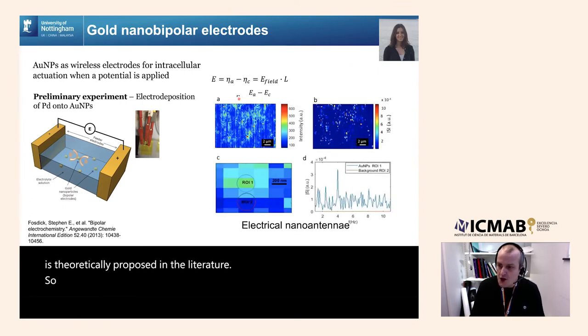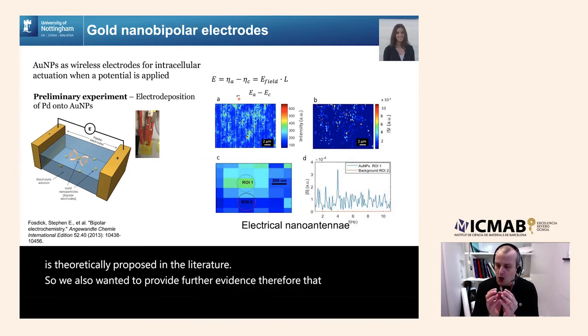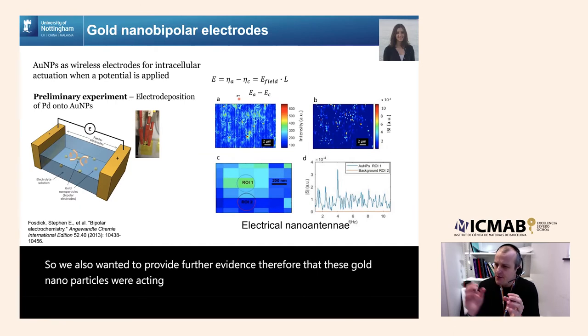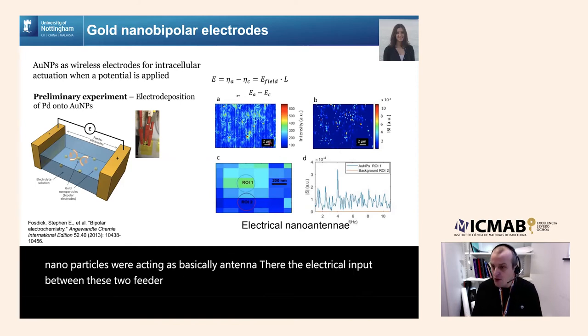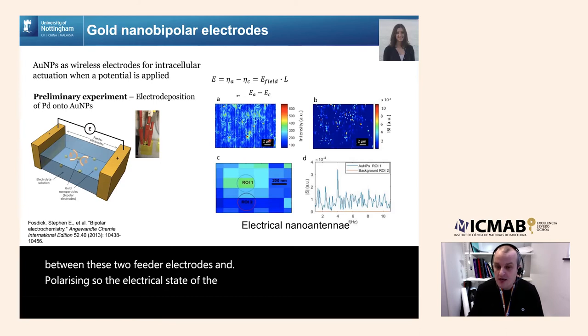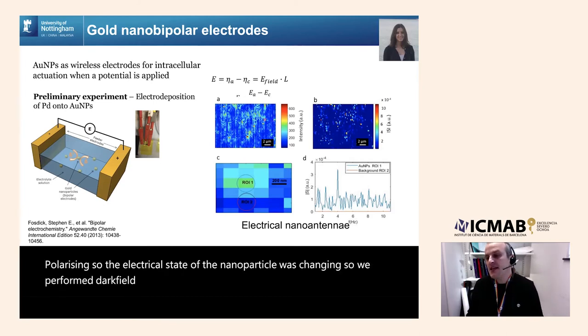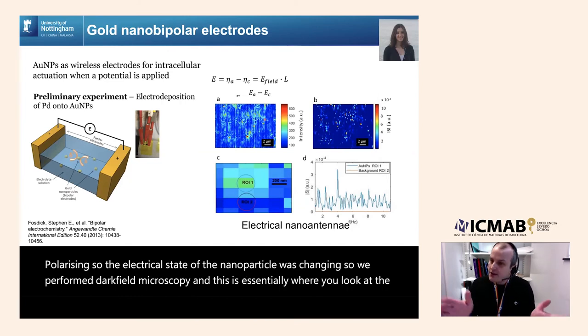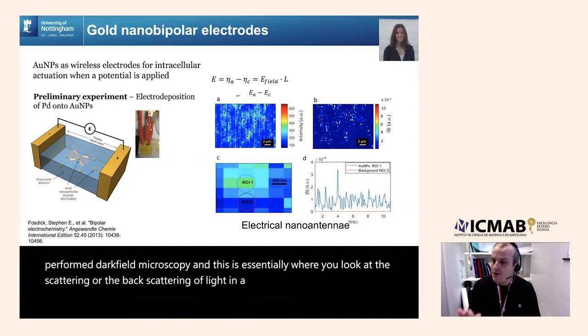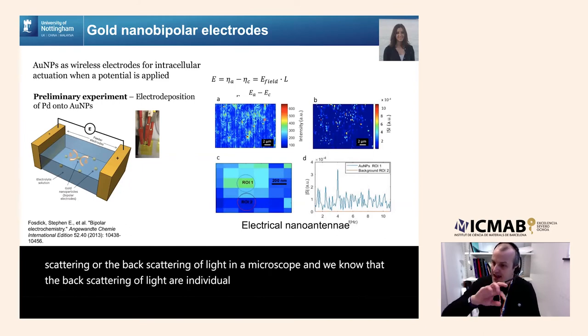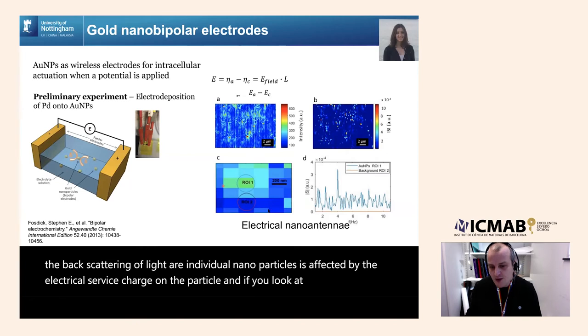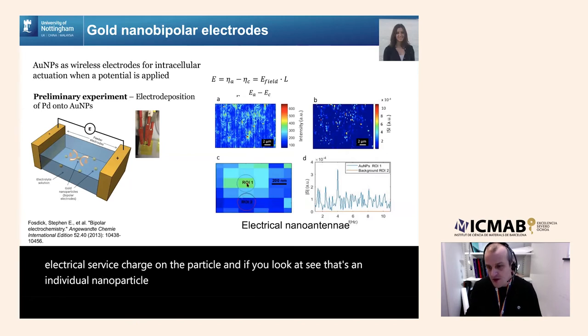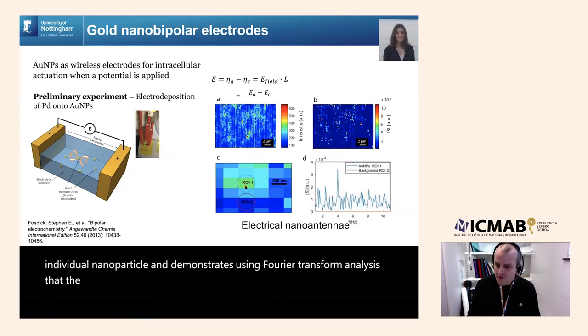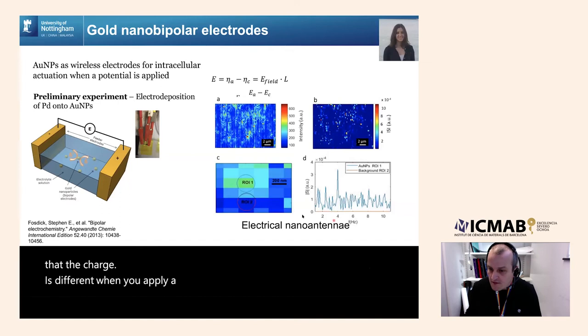We also wanted to provide further evidence, therefore, that these gold nanoparticles were acting as basically antennae. They were sensing the electrical input between these two feeder electrodes and polarizing. So the electrical state of the nanoparticle was changing. So we performed dark field microscopy, and this is essentially where you look at the scattering or the backscattering of light in a microscope. And we know that the backscattering of light at individual nanoparticles is affected by the electrical surface charge on the particle. And if you look at C, that's an individual nanoparticle, and it demonstrates using Fourier transform analysis that the charge is different when you apply a frequency of 4 hertz in this case.